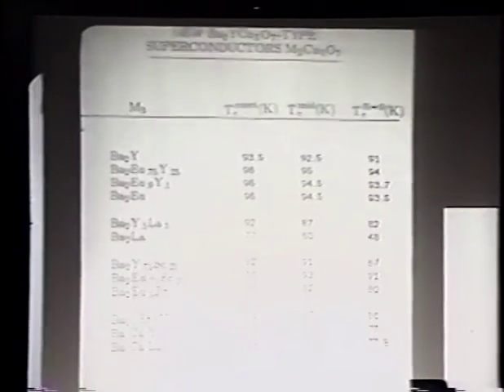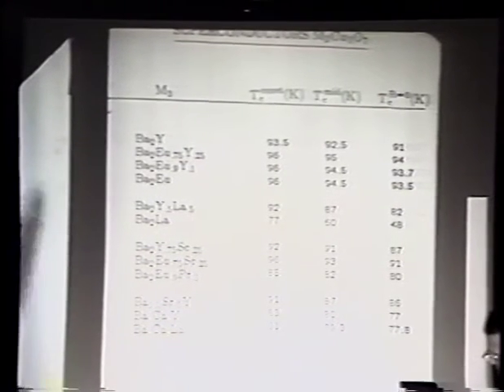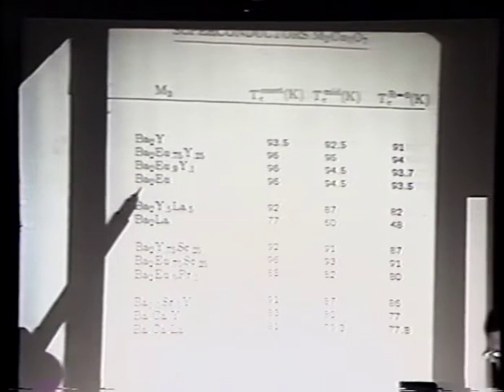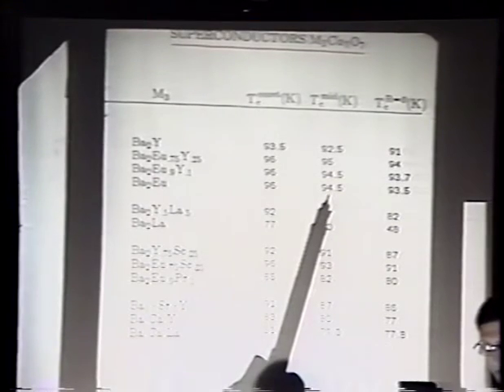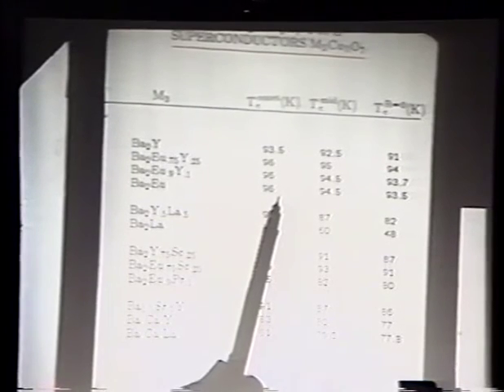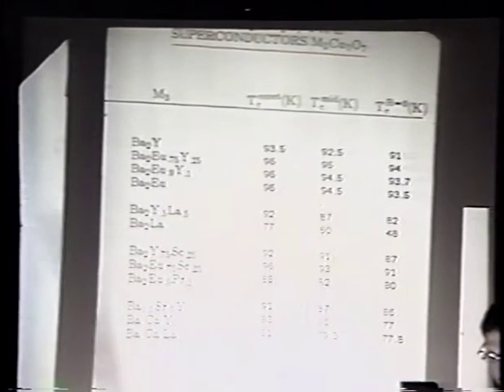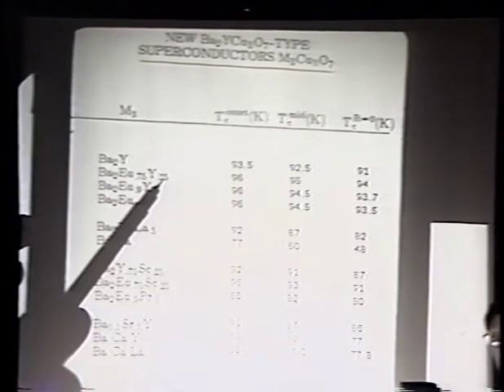We started immediately substituting at different sites, and that's just a preliminary list of compounds we made. Don't focus on all of them. I just like to point out that one can substitute both on the barium side as well as on the yttrium side. And one particular nice substitution, which I like, is the one with europium. Complete substitution with europium drives up TC quite a few degrees, gives a very sharp transition, which is less than 1 degree wide, actually 0.7 degree wide, from 90 to 10% level. I will come back to this particular compound later when I talk about upper critical fields.